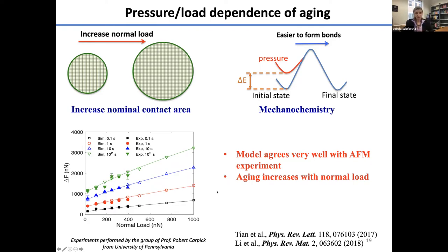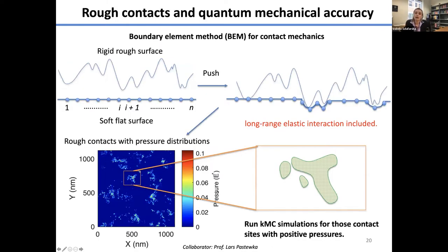So then we say, okay, let's go to multi-asperity contacts. We initially have assumed that a contact is elastic. Considering plasticity and creep is important, but it's another challenge that we want to address in the future, but starting with elastic deformation. We use the boundary element method to describe elastic coupling between the different asperities. So the idea is like there's some asperity pressing in here is going to affect deformation, you know, the neighboring sides because of the elastic coupling. So now this model gives us, for a given normal load, distributions of contact areas and distributions of pressures as shown here.